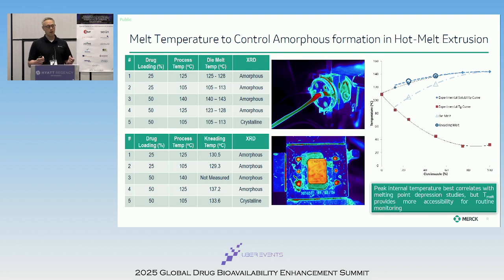And so part of setting the control strategy comes back to how do we identify the appropriate process parameters for manufacturing the solid dispersion. And at Merck, we had done some work looking at characterizing internal temperature within the extruder and then relating that back to the phase diagram. And what you see is that if you do your melting point depression studies and then relate it back to the process section set points, you'll see a deviation, as you can see in the phase diagram on your right.